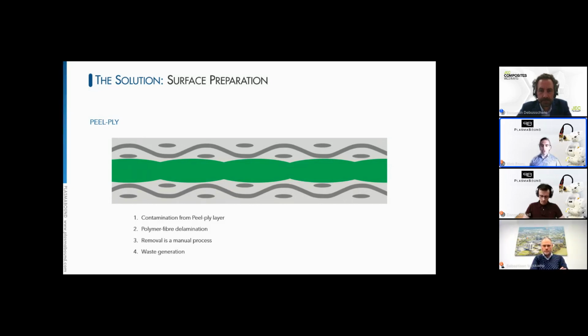The peel-ply removal process can lead to issues with polymer fiber delamination and ingress. And then removal is a manual process, not suitable for high volume continuous manufacturing. And this is the reason why the aerospace industry would primarily be using peel-ply systems, and so would the rail industry. Very large areas, and so they're not concerned with rapid manufacturing.